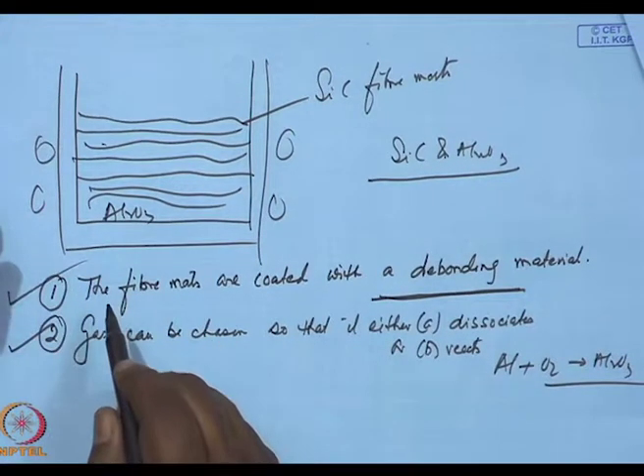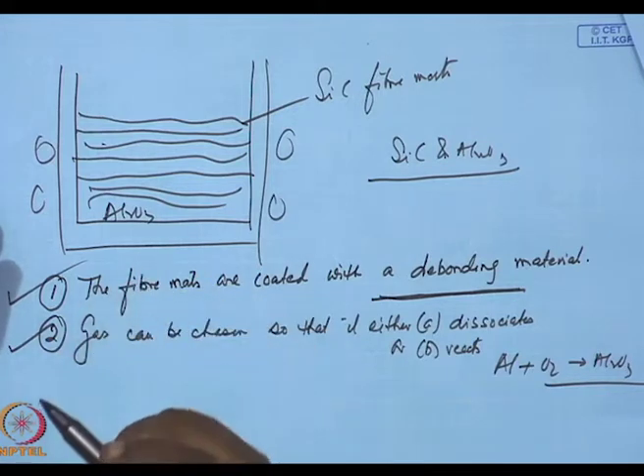So, here by successively vapor infiltrating, reacting, forcing the second phase to form, if there is a liquid, the liquid is oxidized, cooling, then abrading to open up the surface, and again vapor infiltrating. By doing this multiple times, we can get a very dense ceramic fiber reinforced ceramic matrix, which causes reinforcement.